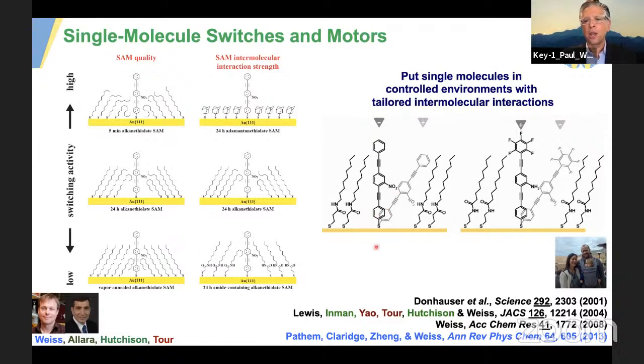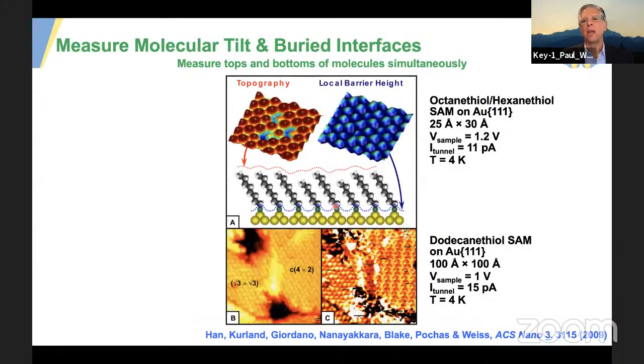And what that taught us was that the contacts, the change in hybridization of that buried contact, was everything. So just like in semiconductors or the other materials we're discussing, the contacts are the relevant functional part. And that led us to develop other new tools, such as the ability to measure the buried interface and the tilt of the molecules, in which we, for instance, simultaneously measured the exposed surface and the bottom bond. And by associating the top with the bottom, we get the absolute polar and azimuthal tilt. That was an experiment that took us about 20 years to make work, but now it gives us the absolute structure and more. We're able to look at buried interfaces, for instance, where there's charge redistribution.